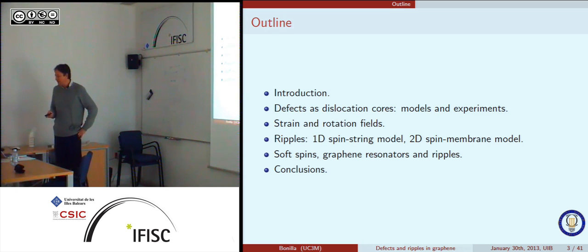And in recent experiments at Oxford, people looked more carefully into this, and they were able to map experimentally the strain or rotation fields about defects. We see that we also have some theory that explains this data and has some surprising elements a posteriori.